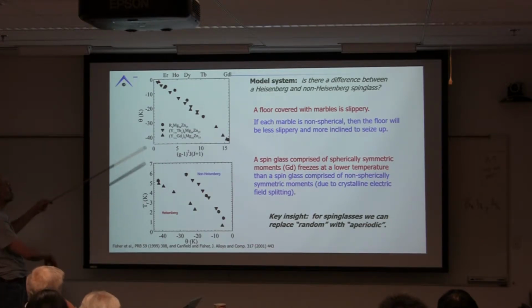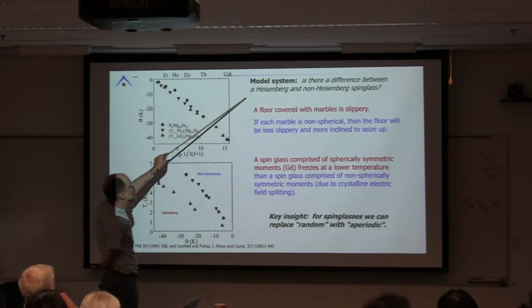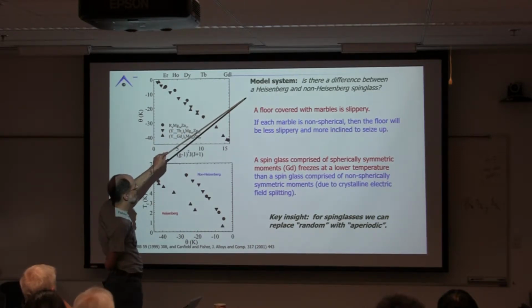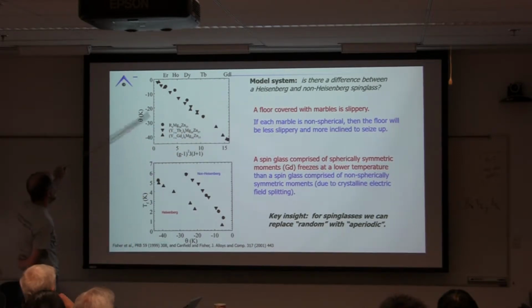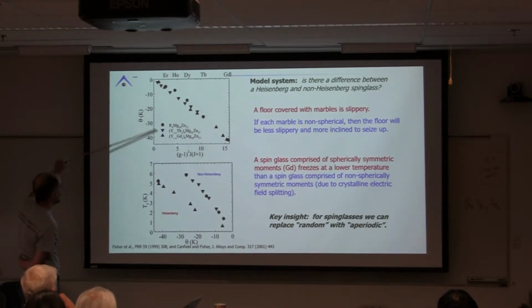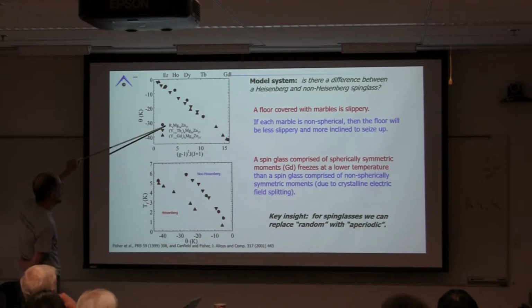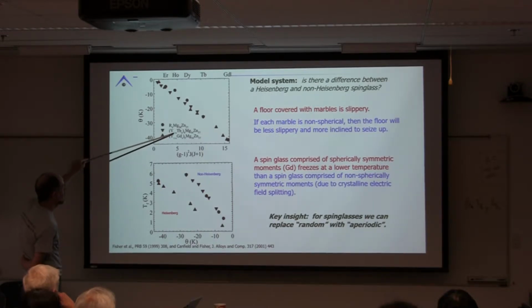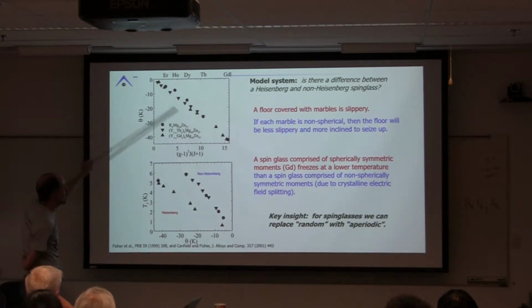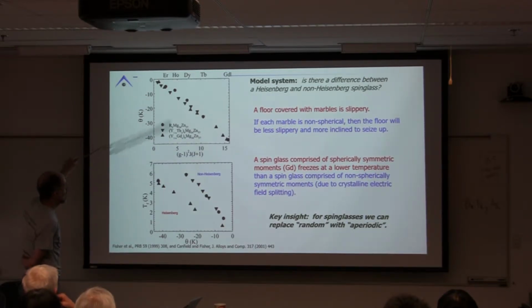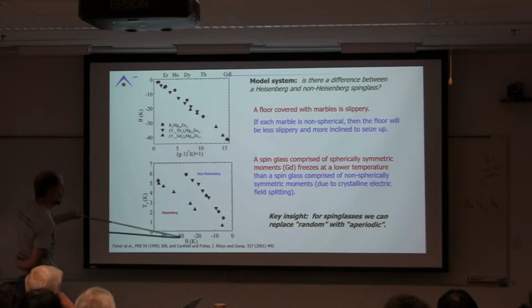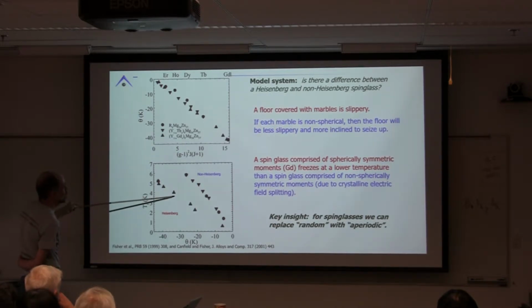Okay? So we could ask, is there a difference between a Heisenberg and a non-Heisenberg spin glass? Okay? So we can have our paramagnetic theta versus de Gennes factor for the pure materials, for a non-magnetic yttrium and CF split terbium, non-magnetic yttrium and non-CF split gadolinium. All of the thetas scale with de Gennes factor, which is what you'd anticipate. On the other hand, if we look at the freezing temperature versus theta, it splits into 2 manifolds.